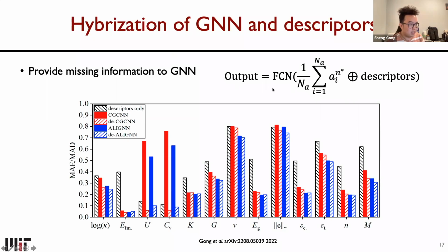output. And we test this scheme with 13 materials properties and by 5 different models, which are descriptors only models, the graph neural network, original graph neural network, and the descriptors hybridized version of these graph neural networks. And we tested a bunch of properties. From left to right is thermal conductivity, total energy of the crystal structure, the phonon internal energy, phonon heat capacity, bulk modulus, shear modulus, Poisson ratio, electronic band gap, the modulus of piezoelectric tensor, electronic dielectric constant, total dielectric constant, refractive index, and the total magnetization.